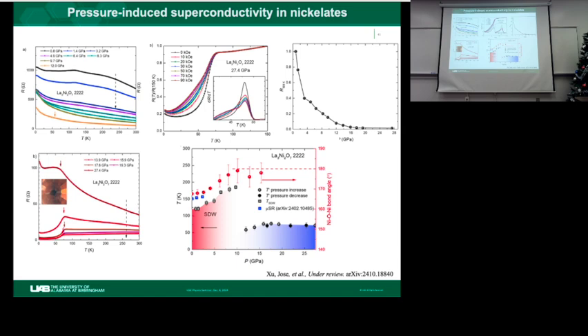Actually, I was kind of curious about that. When you measure your conductivity at high pressure, you also pressurize your copper leads, right? So how do you separate the effects on the sample from the effects of the wires? In other words, could the copper be superconducting under pressure, for example?